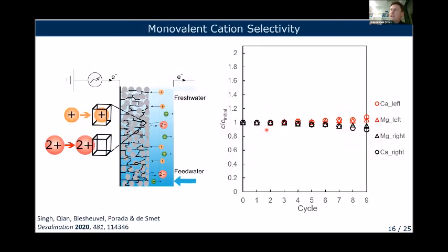And if you then look at the data and you compare the divalent with monovalent data, you would see that in a scheme like this for PBA, where the lattice parameters are such that monovalent ions would fit and the bivalent ones do not, they're too big, you indeed see that also reflected in the data. So this is what you expect based on size, and this is the data. And the data shows us that we have a more or less constant concentration in magnesium and calcium, so the divalent ions, so virtually no absorption, or intercalation as it's called here.